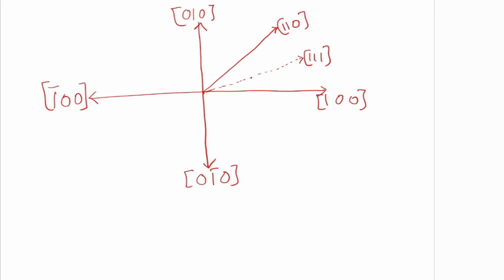So now this is one quadrant. You can do the other quadrants also. Easily you can do it yourself; I think you should better do that. So now I know the surface energy is maximum along this direction, minimum along this direction, like 1, 1, 1. And intermediately it will be along 1, 1, 0, right? You know that gamma 1, 1, 1 is less than gamma 1, 1, 0, less than gamma 1, 0, 0. So I do it.